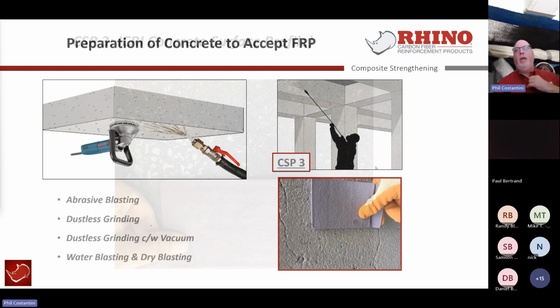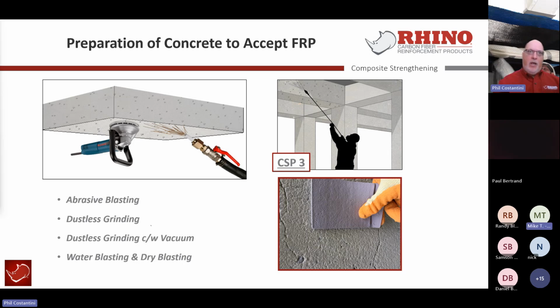How do we do that? How do we get to an orange peel finish? Well, abrasive blasting, which could be sandblasting, dustless grinding with typically a shroud that'll allow for a vacuum so you can create a bit of a dustless environment, especially if you're in real sensitive communities like institutional buildings, hospitals. In hospitals, I would probably recommend hydroblasting if you can, depending on the environmental cleanup afterwards. But water blasting is a very good application.